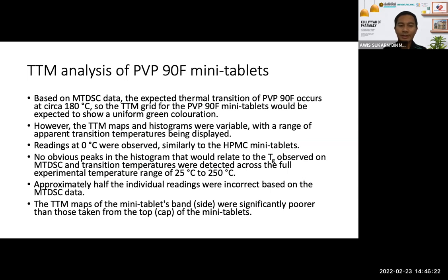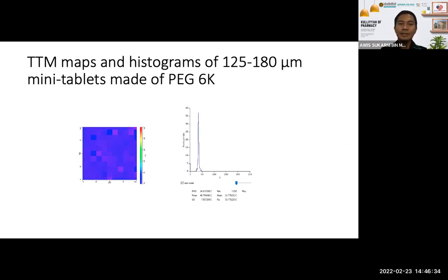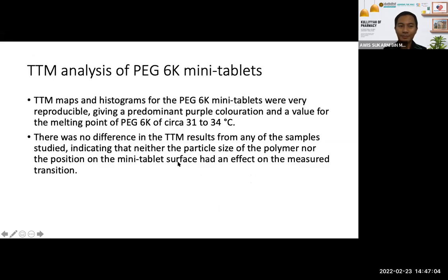And the TTM map of the mini tablet on the band, or the side of the tablet, is significantly poorer compared to the cap of the tablet. Then we move to polyethylene glycol 6000. This one, as you can see, has quite a uniform color. If you look at the histogram, the melting point, or transition temperature, is focused around this region, around 33 degrees Celsius. So it should be a consistent value throughout the surface of the sample that we analyzed.